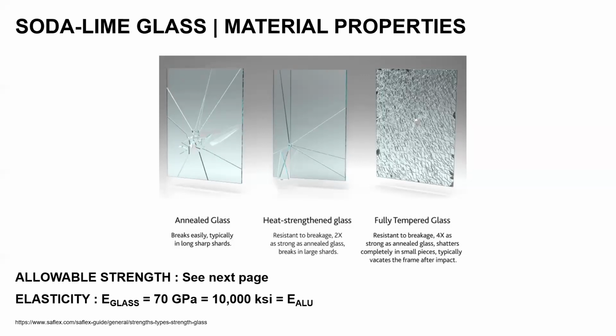As you know, annealed is what we see mostly around us in window glass, and fully tempered is a very fast-cooled product, which confers surface compression to the glass, which makes it much stronger, but also results in breaking into those small pieces, whereas annealed glass typically breaks in larger shards, which can be a good breakage behavior to leverage if desired.